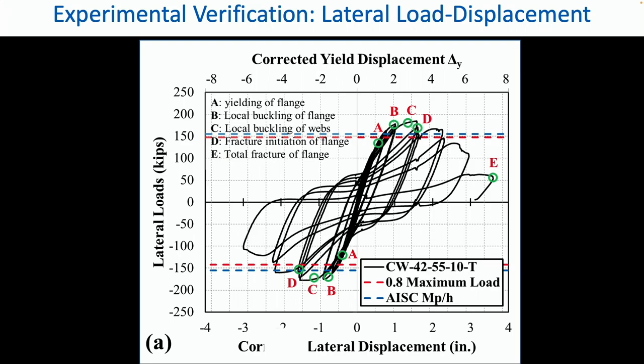And what I've done is gone ahead and identified the occurrence of various events along this load displacement response: the yielding of the flanges, local buckling of the flanges, local buckling of the webs, fracture initiation in the flanges, and then finally, total fracture of the flanges. So this gives us a good sense of what the lateral load versus displacement response of this system is going to be, experimental data that you need to show in order to validate the behavior of the system.